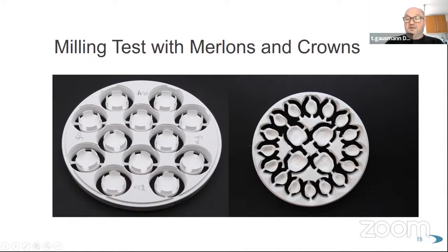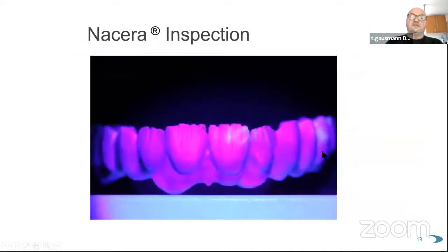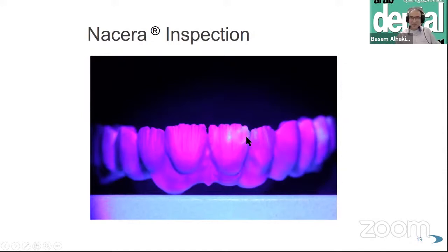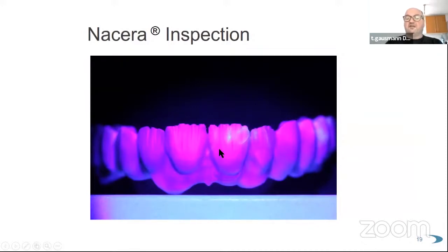That's just another test. And this is called Nacera Inspection. You can see here that you've got a crack running along here and here. So what we did is we took this big bridge and then I heated it up to 1100 degrees in a furnace. And then I took some cold, really cold scissors and inflicted a crack here because I needed a crack to show what this Nacera Inspection does. It's a bath of liquid. You put big work into this liquid and you will detect under ultraviolet light blemishes when there's a crack or something before you go and veneer everything in painful work. You can see that there's something wrong. If everything is good, fine. But it's just another method to test your material and avoid more work.